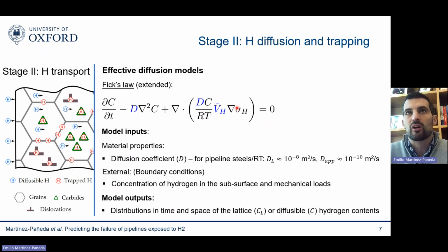And then, of course, the partial molar volume. I'm not going to discuss the quantities that I've discussed before. And, of course, gas constant and temperature. And then we also need some boundary conditions, so some concentration of hydrogen in the subsurface, and that comes from the previous slide. So that comes from the gaseous hydrogen pressure and Sievert's law, and then the mechanical load. So whatever load you're applying, that's going to result in a hydrostatic stress field. And then what do we get out of this model?